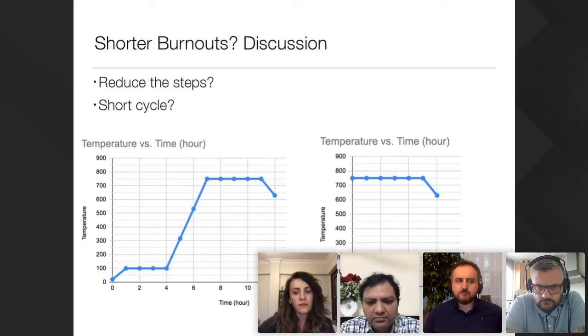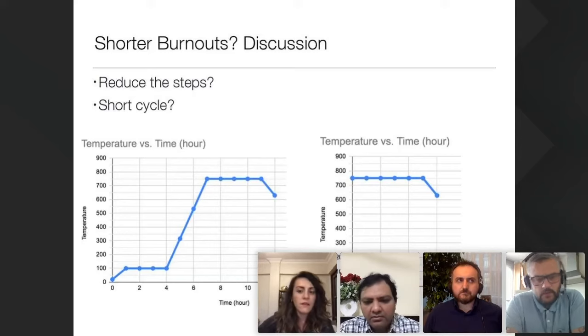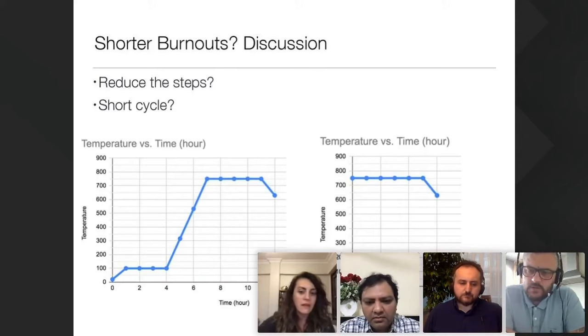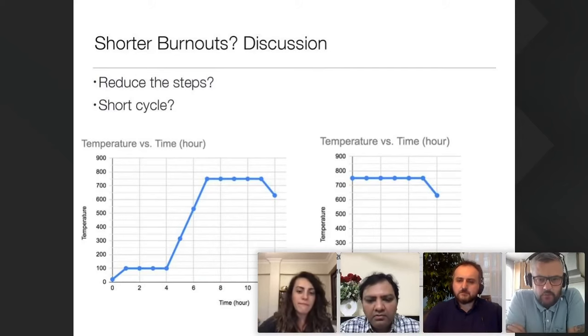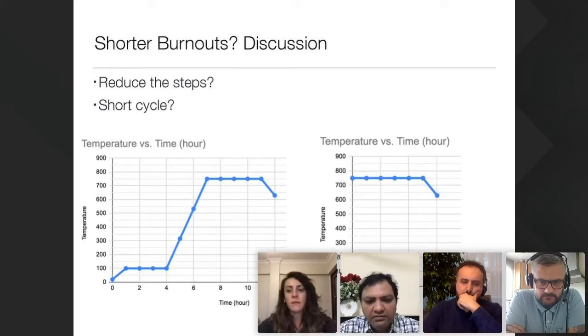Before that, how long should I leave the flask at casting temperature before I cast? Because some say the inside of the flask is hotter than the outside. Minimum 1 hour - no, in the furnaces, you have to keep it 1 hour.